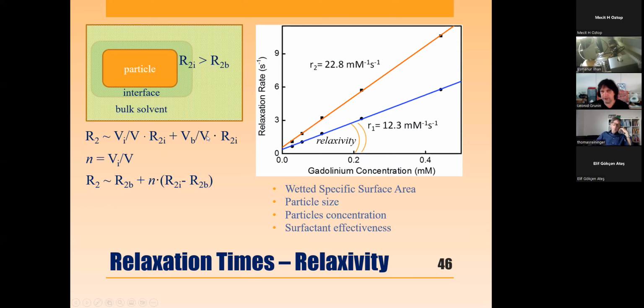Based on such measurements, here are just very simple examples, you can measure the specific surface area, which is extremely important. You just dissolve, put in the NMR, and then you get the number, the particle size, the particle concentration, and also the effectiveness of the surfactants or dispersants. Sometimes particles aggregate to each other and then you have less surface area, but if you add surfactant, they disaggregate and you have more surface area. And this is a case that can be used for estimating the surface area.